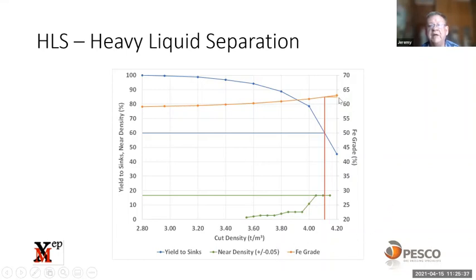So if we wanted to make a 62.5 grade, we intersect the Fe grade line, we go down, we see we need a cut density of 4.1. We can go up and we can move across. We can say we're getting a 60% yield. And then when it intersects the near gravity line, we can see there's less than 20% near gravity. So this wouldn't be a difficult separation.